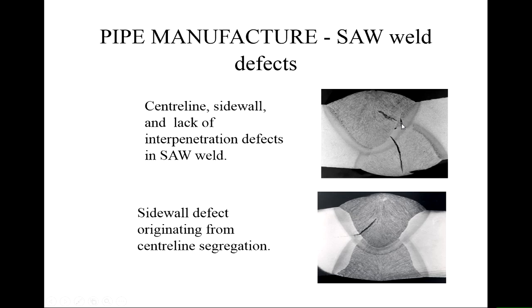So this is the original edge of the material which hasn't actually fused with anything. And then that led to some more complex looking cracks. Sometimes you get a segregation down the middle of the pipe plate from the rolling process, and that can turn into a crack which then runs into the weld. You get those sorts of defects quite widely in submerged arc welding.